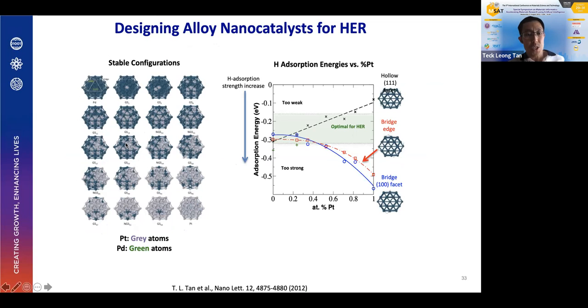Depending on the ratio between platinum and palladium, you can see that there will be some palladium elements on the outer shell, and platinum likes to be in the core, right? So we have this so-called core shell structure. And once you have these structures, we can use them to calculate the hydrogen adsorption energy. You can see that at 100% platinum, because of the size effect, the adsorption energy is out of the optimal range, so the adsorption energy of hydrogen will be too strong. But as we add more and more palladium going to the left, you can see that it tunes the adsorption energy into the optimal region.